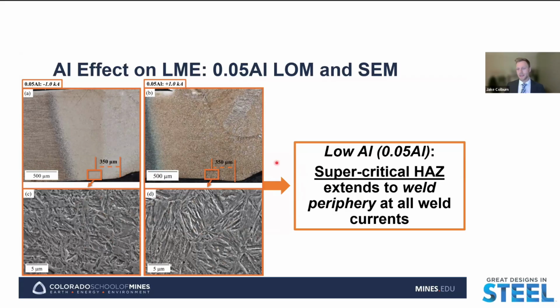But this would indicate, if this is a supercritical heat affected zone, that at the peak temperature of the weld, this region was likely fully austenitic, and then as the weld current stopped and the substrate was rapidly cooled, we get this transformation to martensite and/or bainite present.